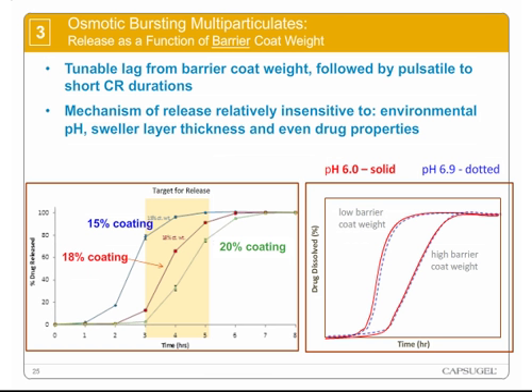So the osmotic bursting multiparticulates hallmark would be what's shown in the left side here. It's a very tunable lag that is only dependent primarily on the barrier coat weight, followed by a pulsatile to short controlled release duration. In this particular case, you can see the lag changing as a function of coating thickness from 15 to 18 to 20% coating. And that lag is followed by essentially 80% of the release of the drug within 2 hours after the lag time has been achieved. Sieving the size of these particles, sharpening that down or changing the size, does sharpen the profile or move it around as desired for any particular product.